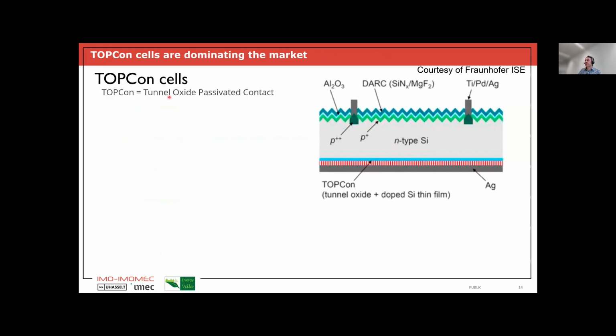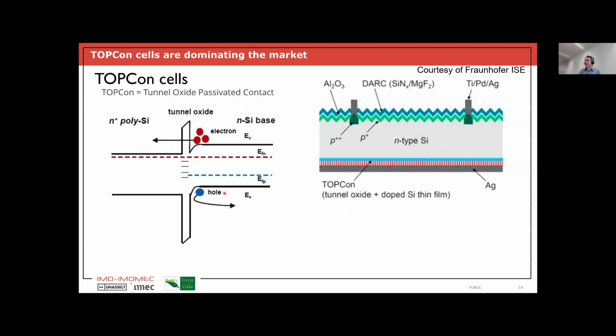TOPCon stands for tunnel oxide passivated contact. And basically, why you can go to higher efficiencies with TOPCon compared to PERC is that we are doing something to the weak point of the PERC device, that is the rear surface passivation of the wafer. So in a TOPCon solar cell, you have at the rear of the silicon wafer a very thin tunnel oxide. And on top of that, a doped, typically polysilicon thin film. And that's why the name arises from this. It's a tunnel oxide passivated contact. You have a tunnel oxide and then a doped layer on top. And this gives you carrier selective contacts.